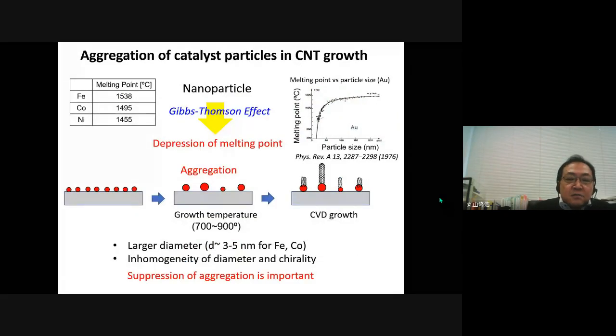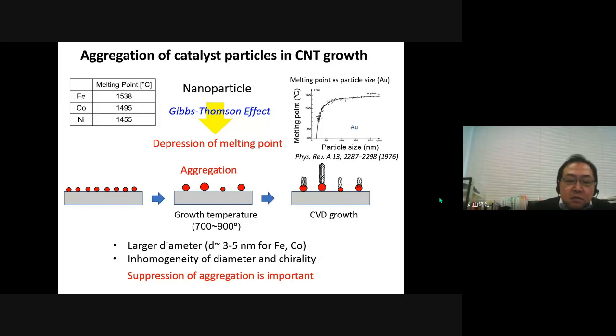The melting points of iron, cobalt, and nickel are about 1,500 degrees C, which are much higher than the growth temperature of carbon nanotubes. However, catalyst particles are nano-sized, which induces the depression of melting points by the Gibbs-Thomson effect. As a result, aggregation of catalyst particles occurs, which leads to the enlargement of carbon nanotube diameter, and both diameter and chirality distribution become inhomogeneous. So it is important to suppress the aggregation of catalyst particles.